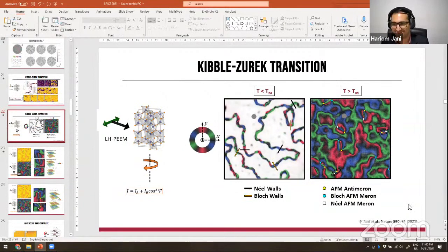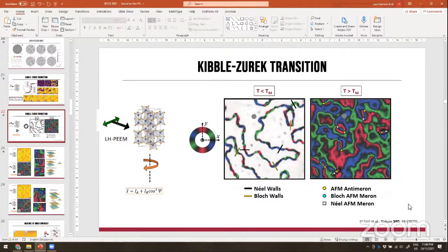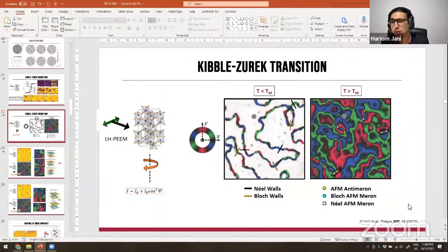Okay, beautiful. But if you take another sample, then the location of all these things will be different, right? Absolutely, because there is nothing fixed by the technique itself or the growth process itself. The Kibble-Zurek transition is a probabilistic process, and therefore the places where these would be nucleated are probabilistic. So our intention here in using this transition was to show that the system is topologically rich. However, if we want to exploit it experimentally for racetracks, it would be important to use other techniques which are athermal to guide the stabilization of these textures.